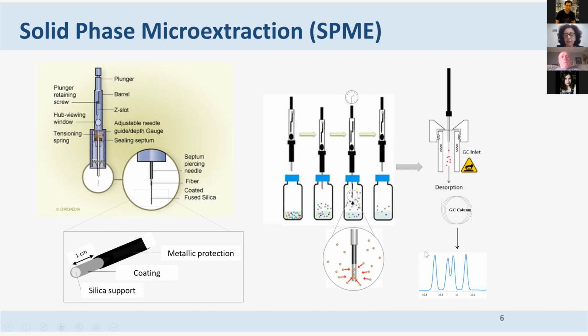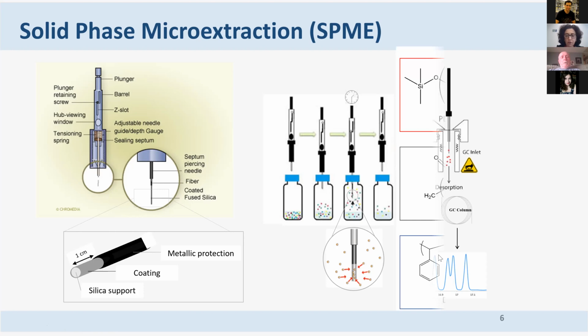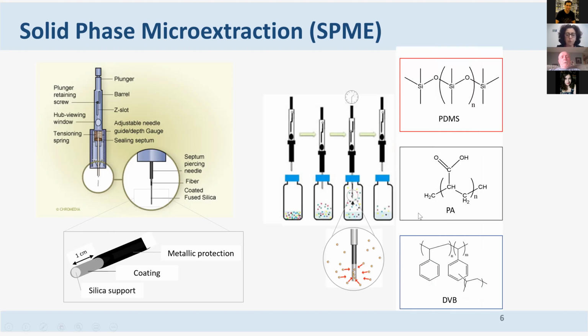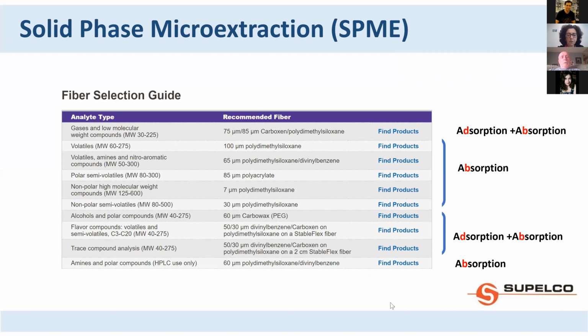Of course, this is a commercial technique, yet there are many fibers that can be used for this purpose. Typically, there are only three polymers that can be used for this application: PDMS, polydimethylsiloxane, polyacrylate, and polydivinylbenzene. One can wonder, for an application as good as this one, as widely used as this one, only three polymers are typically used. If we take a look at the Supelco catalog, which is the brand that supplies these fibers, we can see that they have fibers that are produced by polymers. They are made of polymers only. And there are others that have carbons in them, Carboxen.